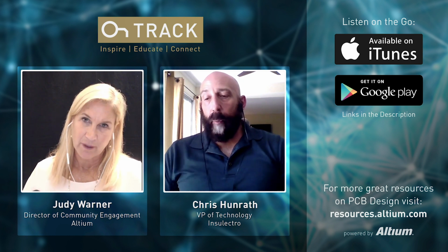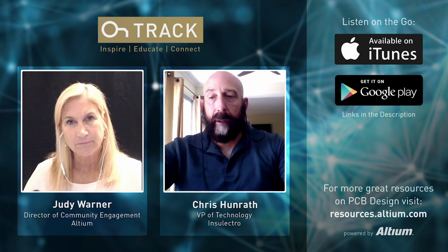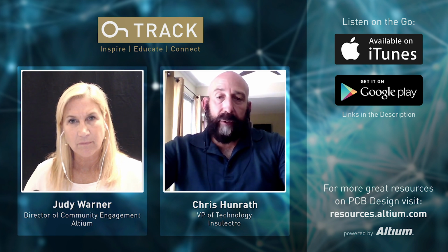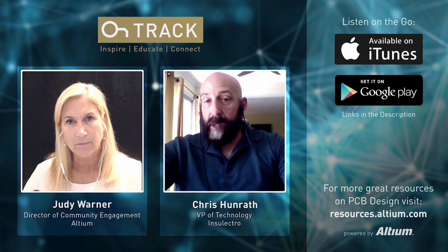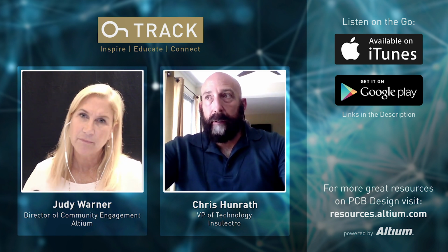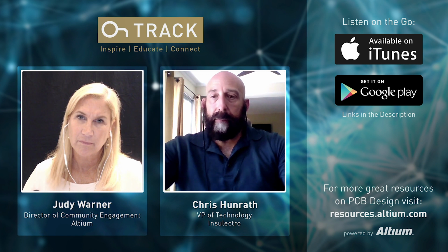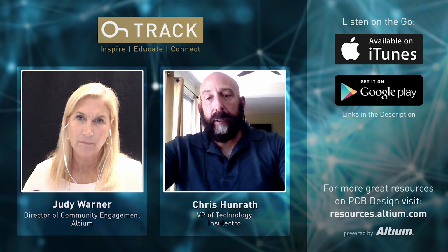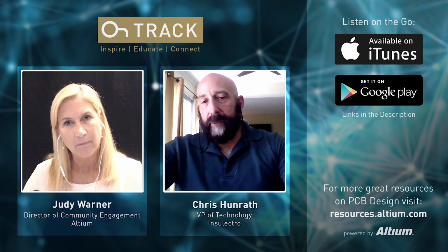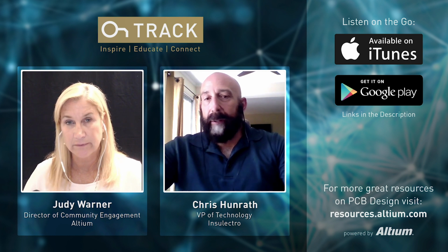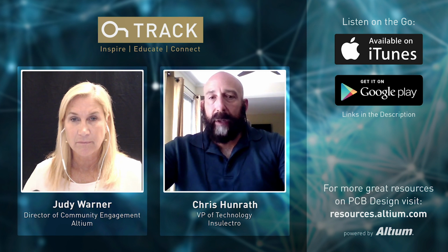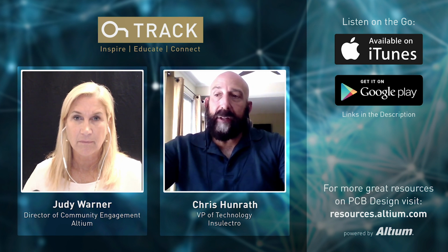Interesting. One of the things too, we talked about bleeding some printed electronic technology into PCBs. I've been involved in some conversations with DuPont. They have a very interesting liquid polyimide technology that cures at 300 Fahrenheit, which is very low. And we're exploring the opportunity to use that in lieu of solder mask, because solder mask on the surface is becoming an issue. Its loss characteristics are not great. It's an epoxy acrylic hybrid, and it doesn't have great loss characteristics.